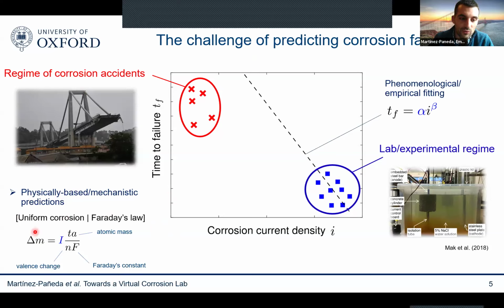Basically, you get a change in mass loss as a function of the corrosion current density, but also as a function of some physical parameters: atomic mass, valence change, Faraday's constant. These are numbers that we know. So if we sample the corrosion current density over time, we can predict the mass loss. And this expression works very well. We can calibrate that expression with a quick experiment, and we can see that it works out pretty well over long periods of time.